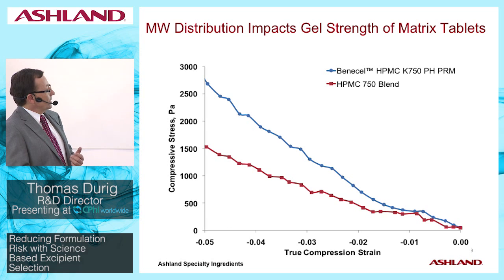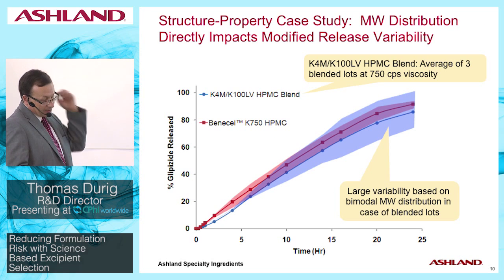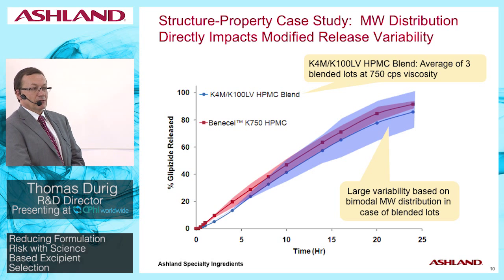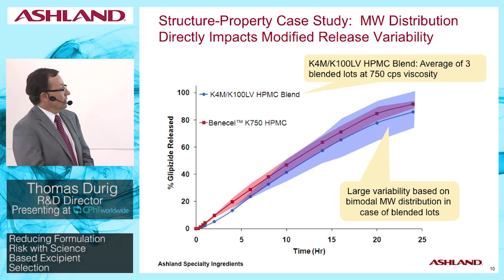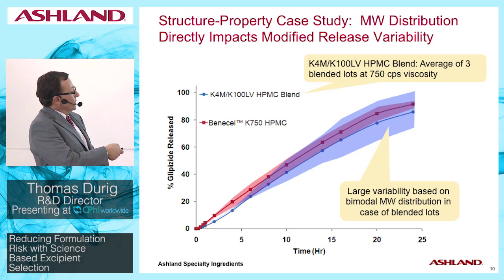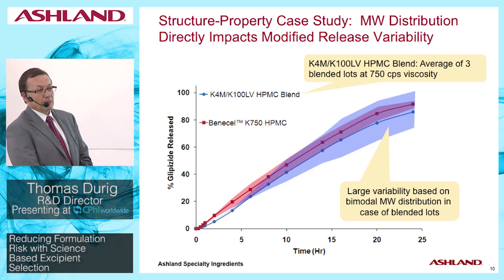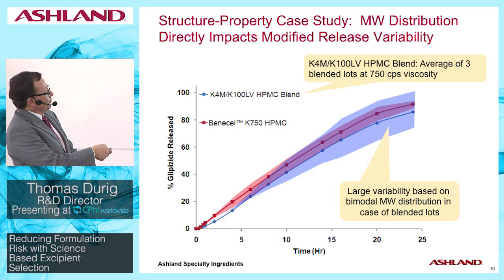And this directly impacts the release profiles, as you can see here, because the gel strength impacts the erosion as well as the variability of the erosion of the tablets. And clearly you can see here that the custom-made Benecel K750, the one with the unimodal molecular weight distribution, has a far narrower variability than this very variable blend of the two polymers.